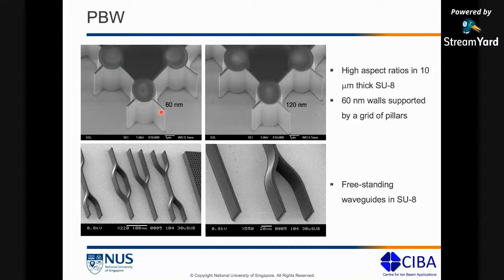So we can have these high aspect ratio structures if we are able to focus the beam spot down to sub 50 nanometers, right? So this is one of the distinct advantages of proton beam writing. We in fact even have created micro and nano channels now for microfluidics and nanofluidic research projects. But again, the downside to proton beam writing is that it's not something that can be set up in a small room. We need an accelerator to run the beam through the beam lines and into the chamber. So that's proton beam writing.